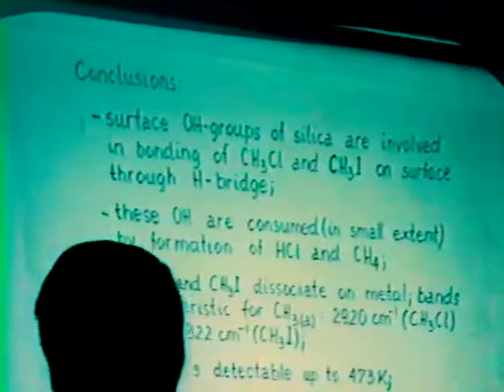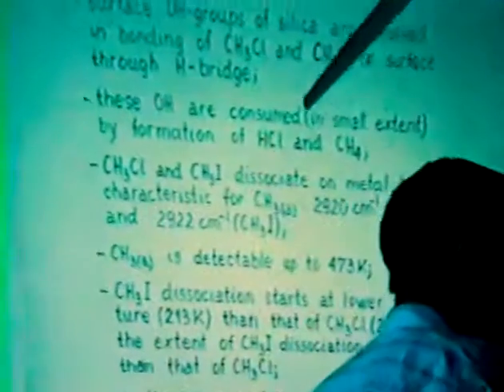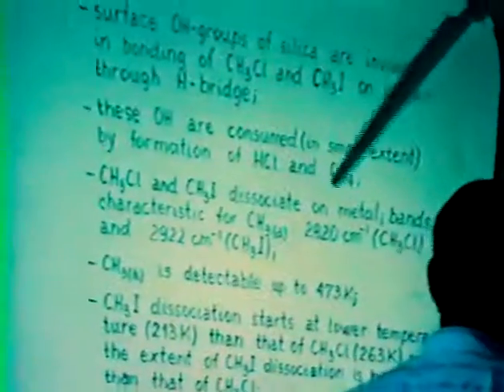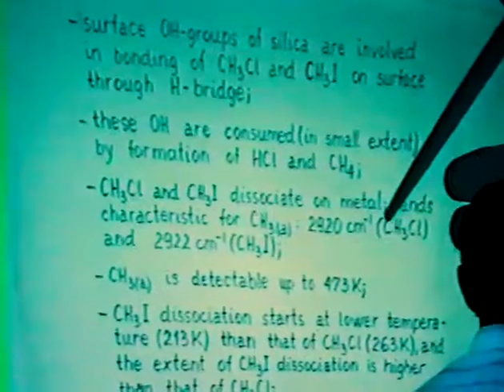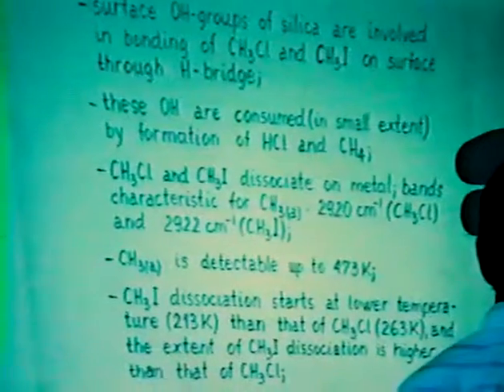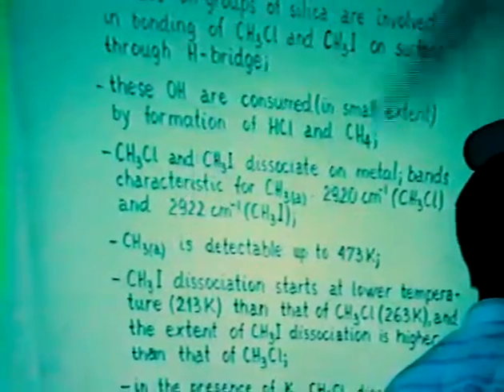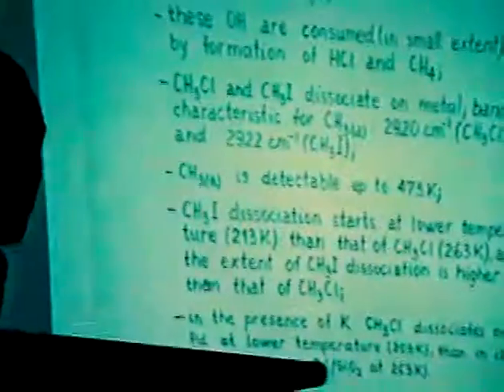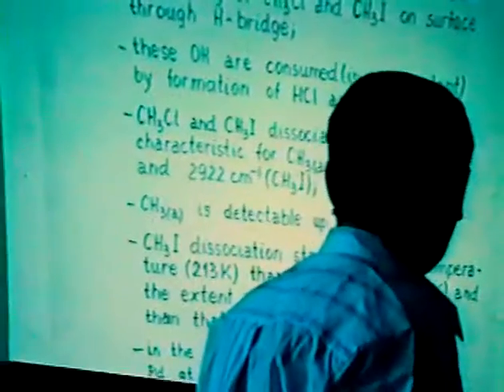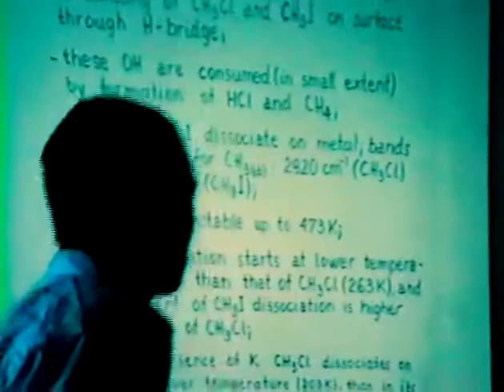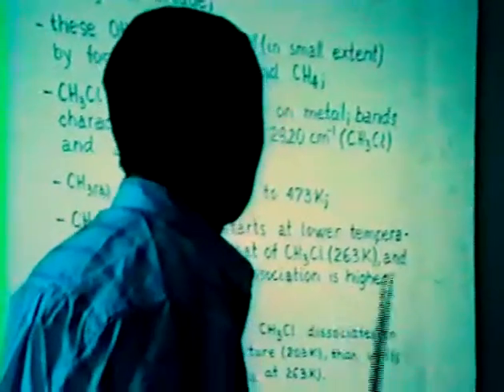Both alkyl halides can dissociate on the metal, giving bands characteristic for surface adsorbed methyl group. In the case of methyl chloride, it is 2920 wave number, and in the case of methyl iodide, 2922 wave number. The adsorbed methyl group is detectable up to 473 Kelvin. And as I have shown lately, the dissociation of methyl iodide starts at lower temperature than that of methyl chloride, and the extent of its dissociation is higher as the intensity of the band is also higher.